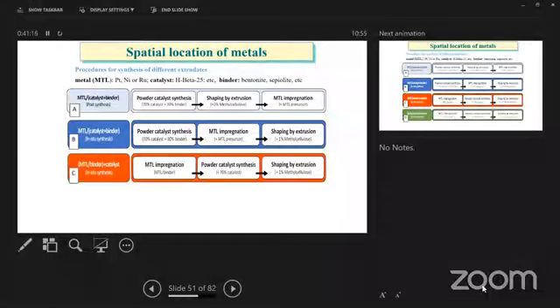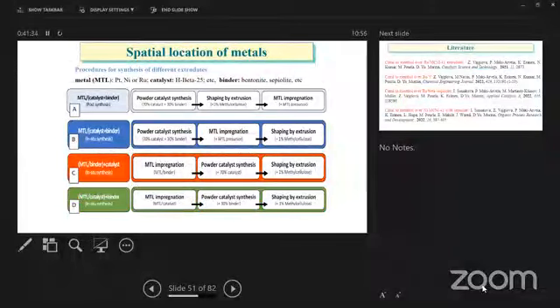This is one idea. The second, we have the mixture of the zeolite and the binder, and then we do impregnation. And then the next step is extrusion. The third option can be we just impregnate the binder, so there is the binder with the metal. Then we add the zeolite and then we do shaping. Clear. And then the last option would be impregnating the metal on the zeolite, adding then the binder, and then doing extrusion. You see, so there are at least 4 options. So it gave us many more possibilities than in the case of Brian de Jong, who once again used the commercial extrudates.